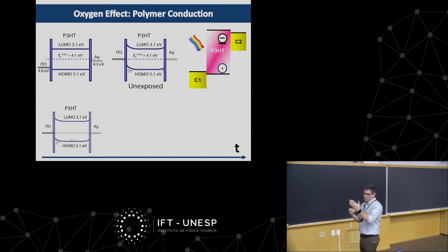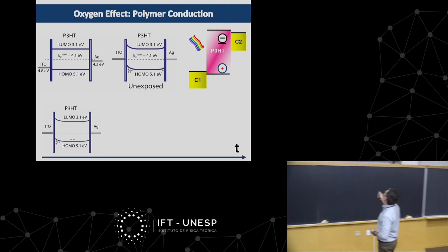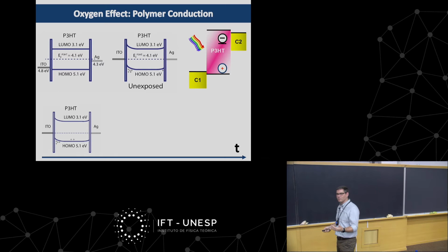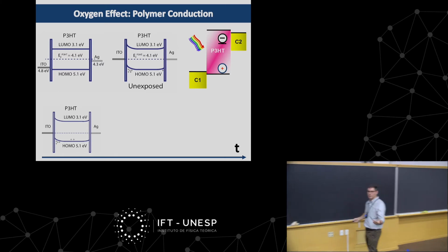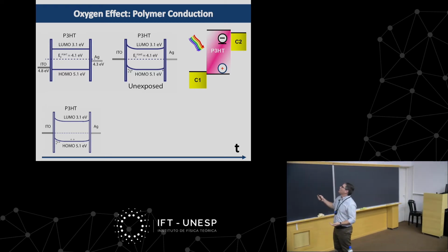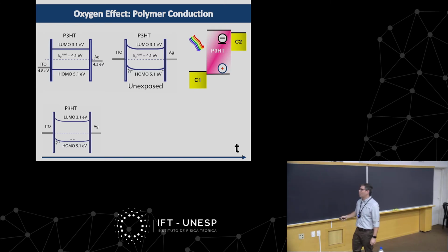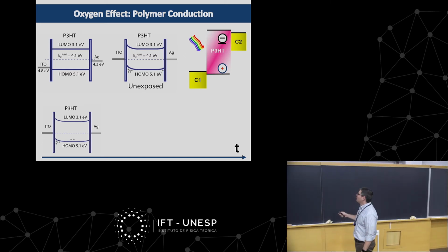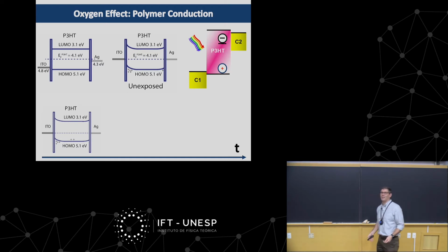And they can recombine, but if there is an electron around, as I just mentioned to you, the oxygen will capture this electron, will trap it, and will actually p-dope my P3HT polymer. And by p-doping the polymer, what I'm doing is introducing charges at the HOMO of my material, which is the valence band. And when you introduce doping charges on your material, what happens to your Fermi level?